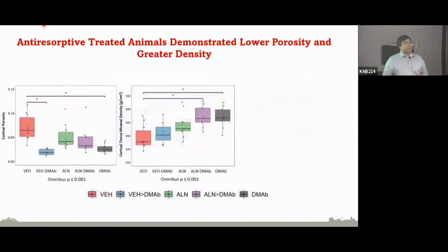I think our results for this part especially were really clear, and they really did match our expectations. So the first thing we saw is this plot here, which is a plot of cortical porosity across the different groups. And we saw clearly that treatment with drug, and particularly the vehicle DMAB and the DMAB alone groups, had much lower porosity than the animals that only got vehicle. We also saw some nice improvements in tissue mineral density. And in this case, it was the DMAB alone and the 6-month alendronate and 6-month DMAB groups that had the statistically significant post-hoc comparisons.